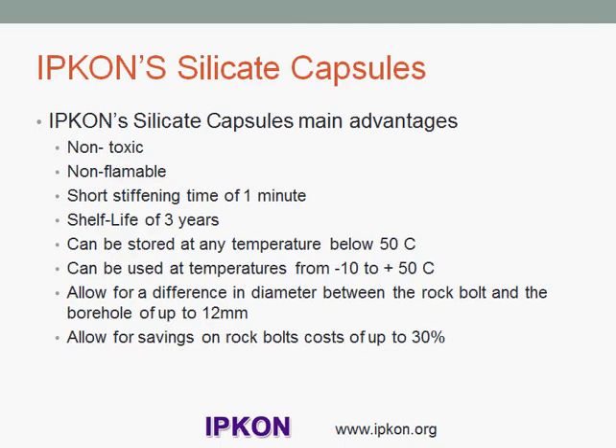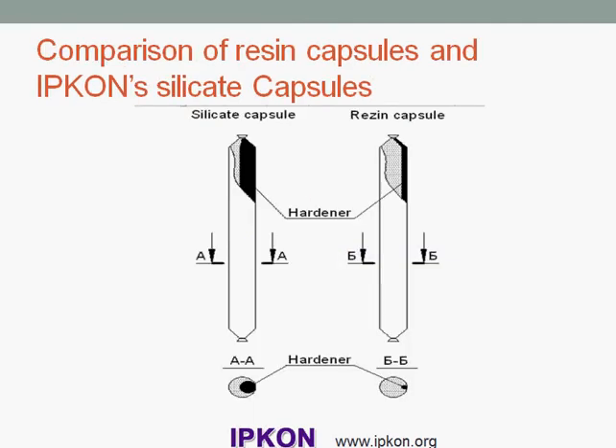Let me explain this. With IPKON silicate capsules, the fixing agent is inside another capsule of a diameter of 17 millimeters. In comparison, in resin capsules, the inside capsule has a diameter of 4 to 5 millimeters. In silicate capsules, the diameter of 17 millimeters of the inside capsule ensures that this inside capsule will be broken and the fixing agent will be released and will mix with the hardener.